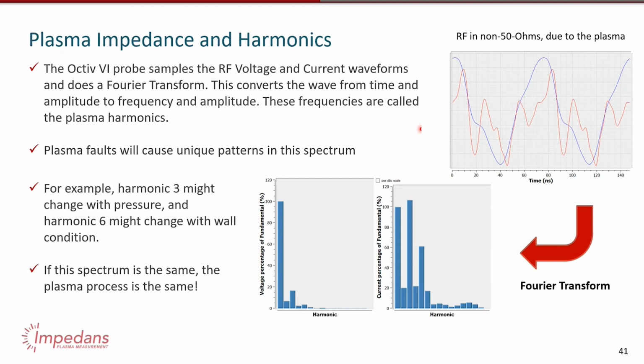Changes in that circuit will change the impedance that you measure, but these harmonics are really sensitive to changes in that impedance, and they're specific to the different things that change that I mentioned on the previous slide. So by monitoring these harmonic levels, you can get really high sensitivity to plasma chamber changes. And that's usually what we recommend for process repeatability monitoring and so on.